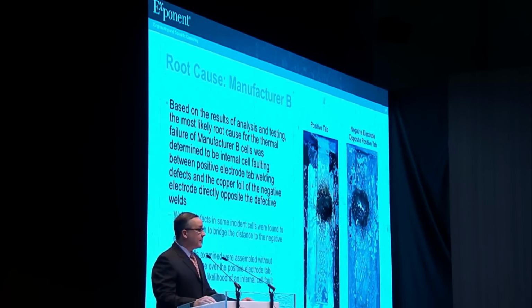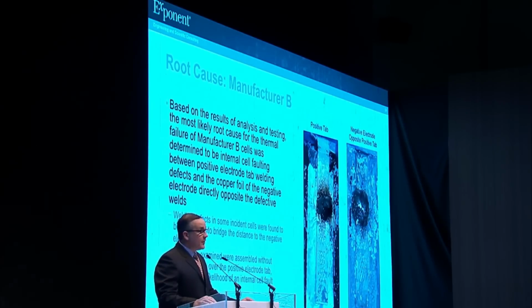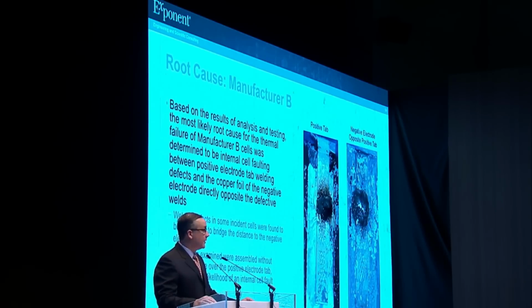The weld defects were related to the height of the features left behind by the ultrasonic welder used to attach the positive tab to the positive electrode current collector. The height of some of these features exceeded 80 microns, the distance from the flat surface of the positive tab to the surface of the opposing negative electrode current collector. This distance was defined by the thickness of a layer of protective tape, the separator membrane of the cell, and the thickness of the negative active material coating.